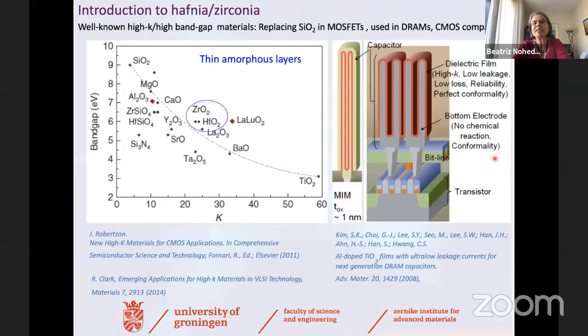And you can see here in this example, the capacitors using a 1 nanometer oxide layer of hafnia that is showing high K, low leakage, low loss, and perfect conformality because they can be grown using ALD or CSD methods. So they have been used, and they are integrated into the CMOS process, which is, of course, a huge advantage.